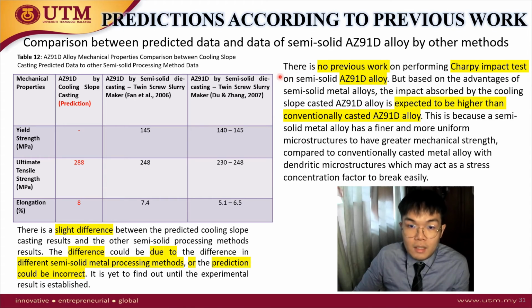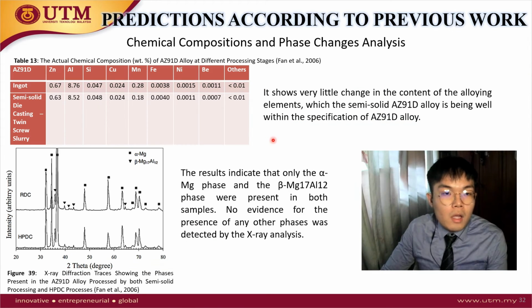For the Charpy impact test, there is no previous work on performing it yet. But based on the advantages of semi-solid metal alloys, the impact absorbed by the cooling slope cast AZ91D alloy is expected to be higher than the conventionally cast alloy. This is because semi-solid metal alloy has a finer and more uniform microstructure to have a greater mechanical strength compared to conventionally cast metal alloy with dendritic microstructure, which the dendrite is acting as a stress concentration factor to break easily. And we move on to chemical compositions and the phase changes analysis.